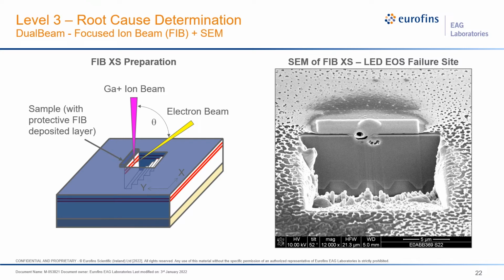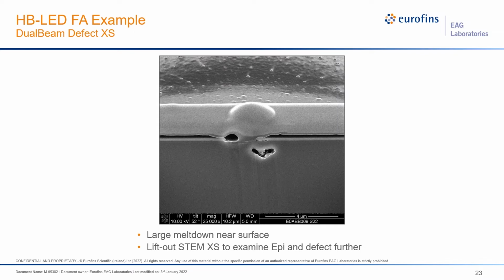So then we can see more clearly in cross-section how this defect evolves through the epitaxy. In this case, you can see the patterned sapphire substrate. This is the GaN buffer region, and then the active layers are up here near the surface. From this, we can really see that we have a large meltdown, what we sort of assessed from the surface, and you can see that it extends a micron or so into the sample.